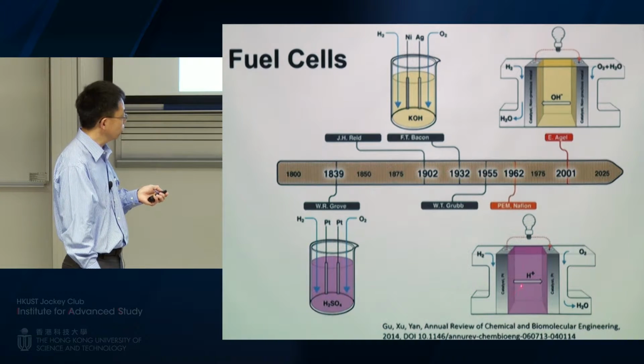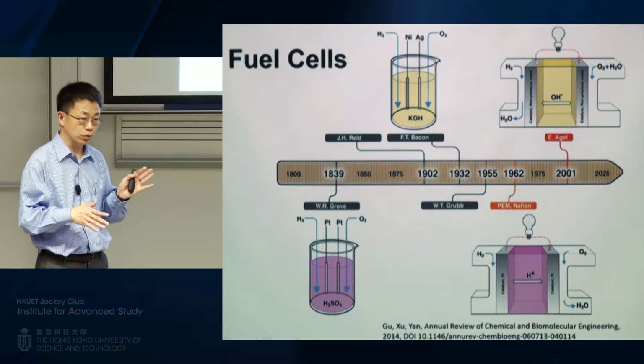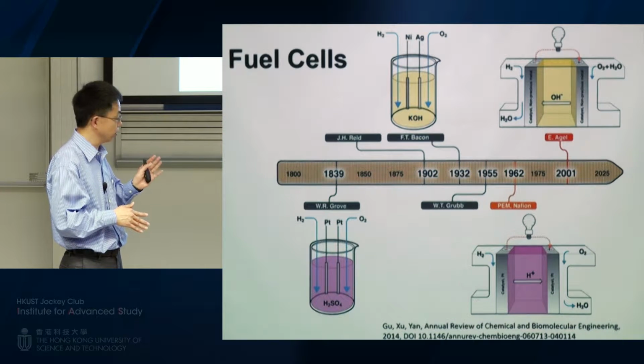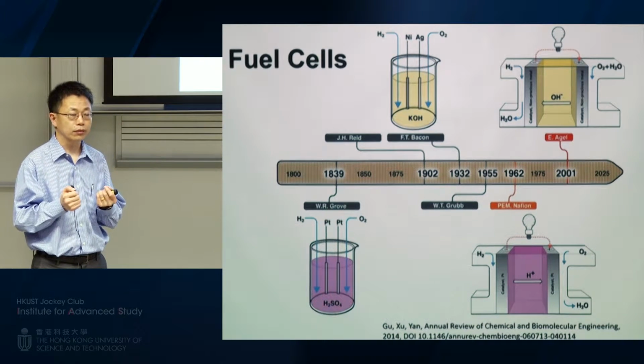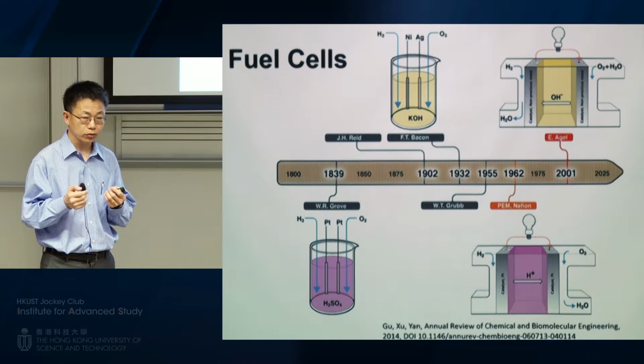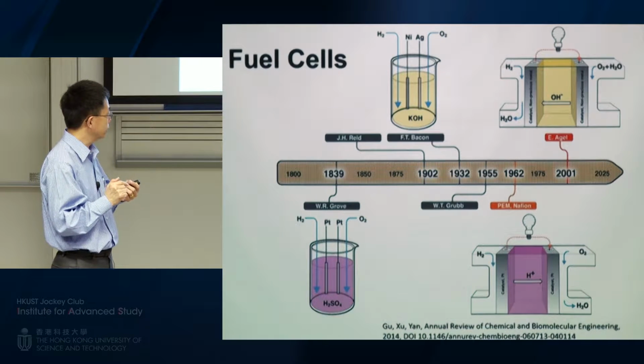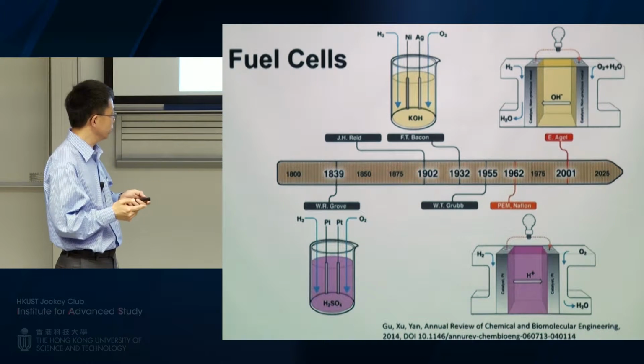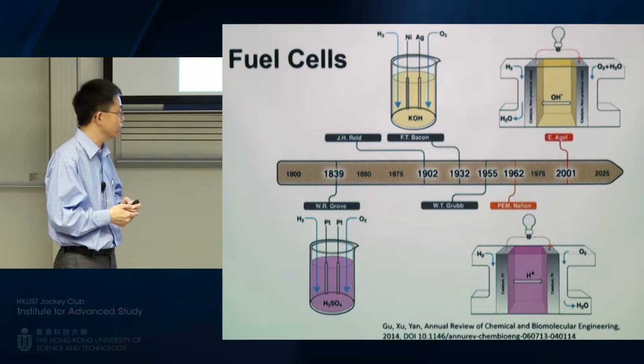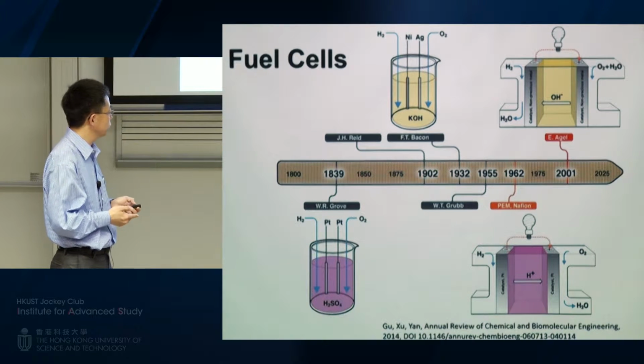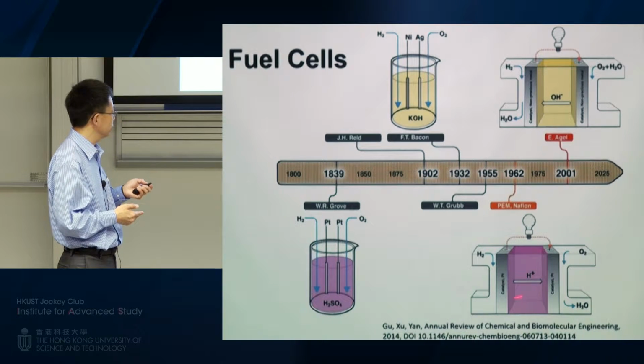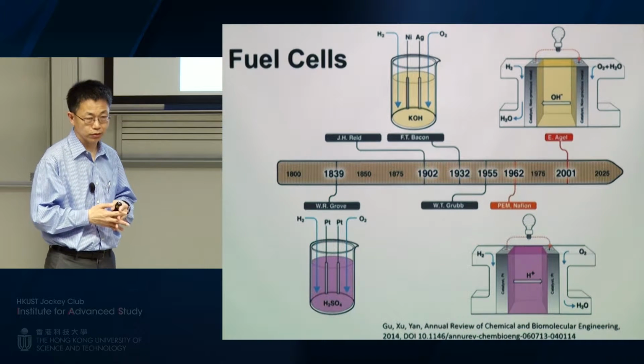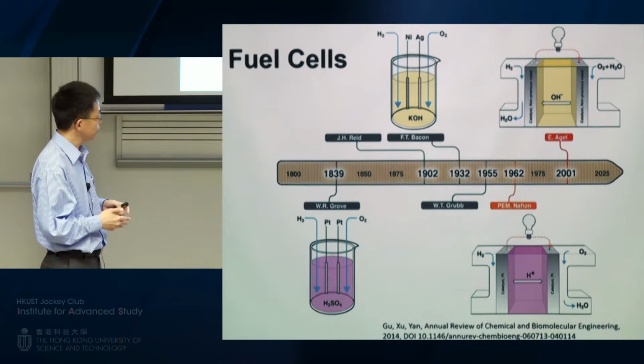I think that's when DuPont came up with this wonderful polymer, Nafion. I think the field converged to this proton exchange membrane fuel cell because Nafion is a wonderful proton conductor, very conductive, and it's also very stable thermally, mechanically, and chemically. So that's just wonderful. I think probably everyone, including myself, thought that was it. So let's just do proton exchange membrane fuel cell. But it turns out, as long as you stay with acid, be it liquid or solid, you're going to need platinum. You can reduce it, but it looks like it's necessary to have some platinum in there.